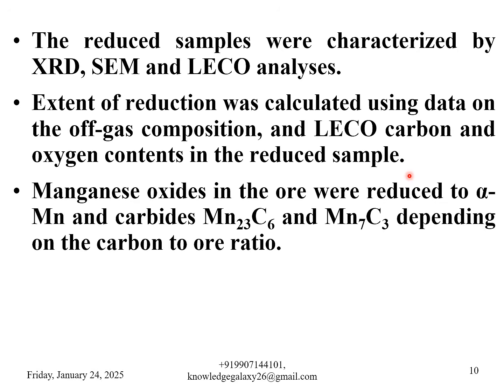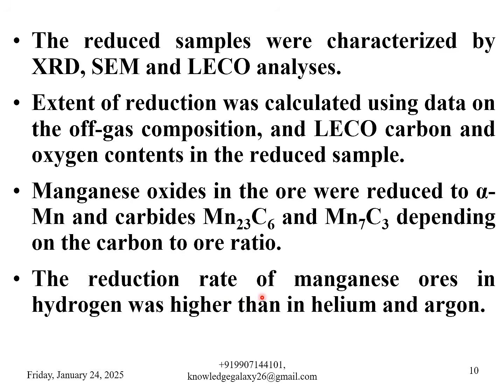Manganese oxides in the ore were reduced to alpha manganese and carbides, that is Mn23C6 and Mn7C3, depending on the carbon to ore ratio. The reduction rate of manganese ores in hydrogen was higher than in helium and argon. So now we will be having the introduction and go deep in the presentation step by step.